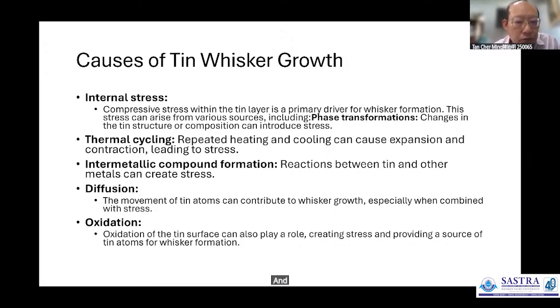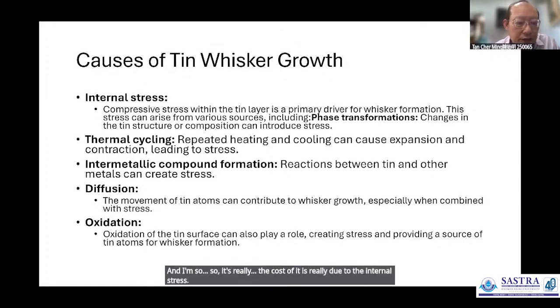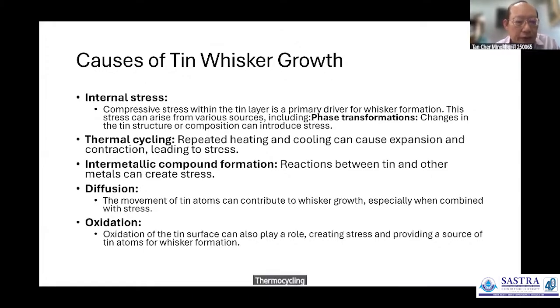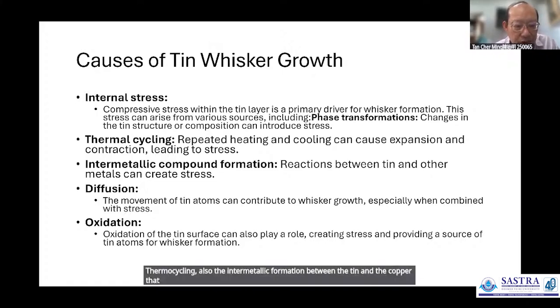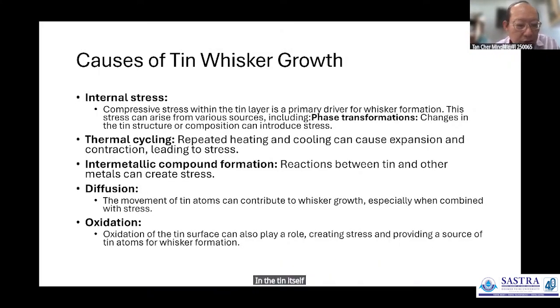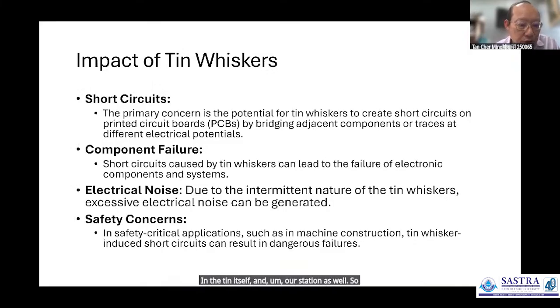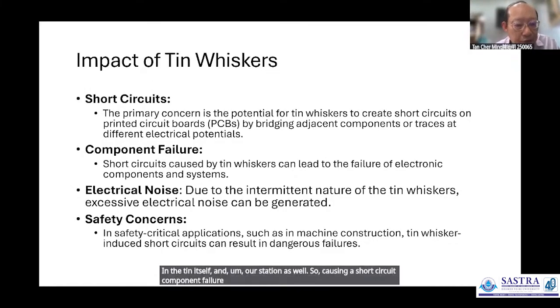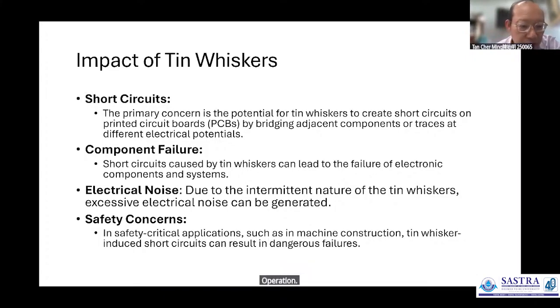And so the cause of it is really due to the internal stress, thermal cycling, also the intermetallic formation between the tin and the copper that were causing a stress in the tin itself, and oxidation as well. So it's causing a short circuit, component failure, and before it happens, maybe you start to see a lot of electrical noise, or sometimes even the intermittent operation. So it is a safety concern because it causes short circuit.